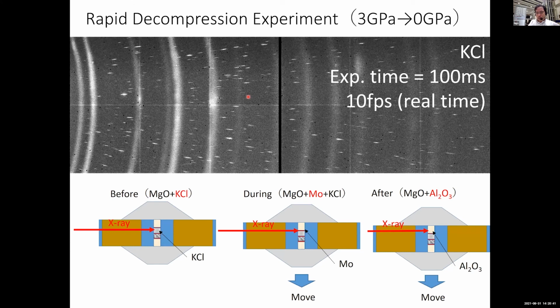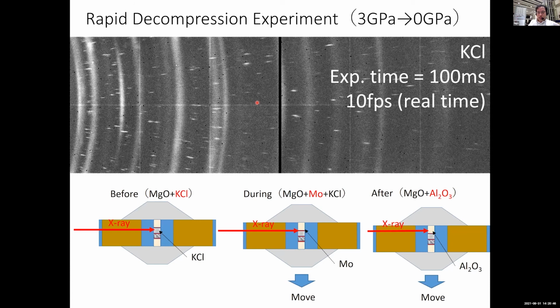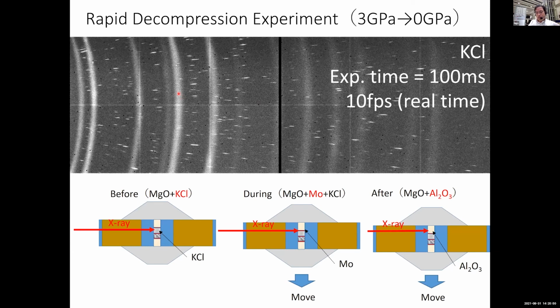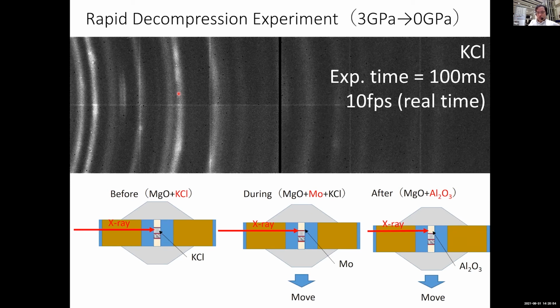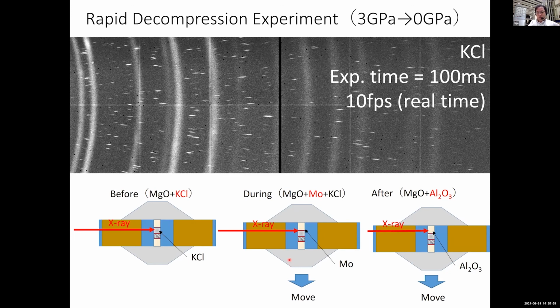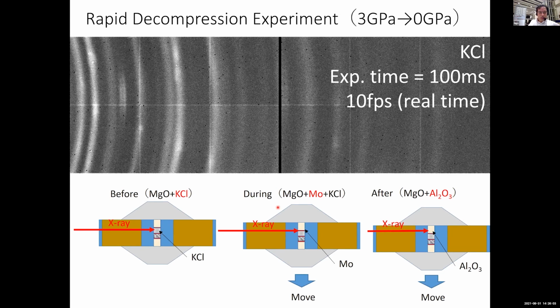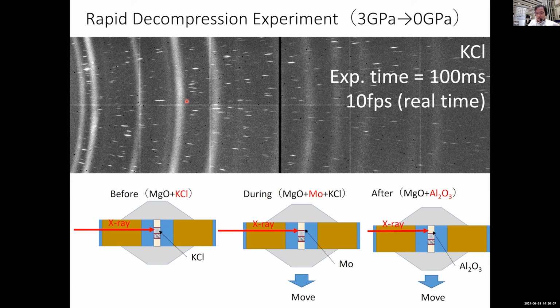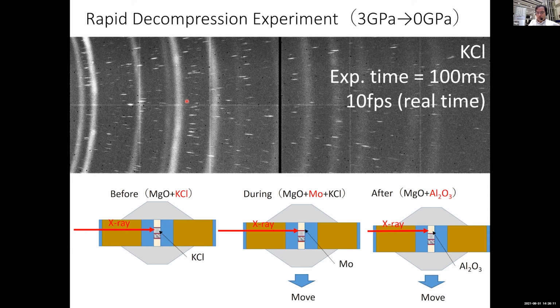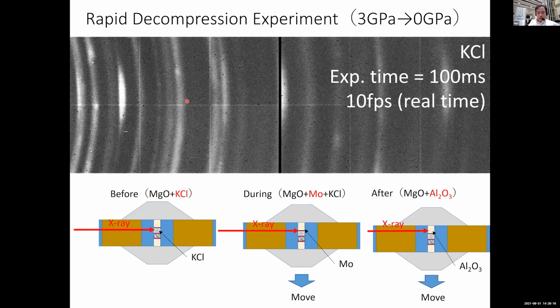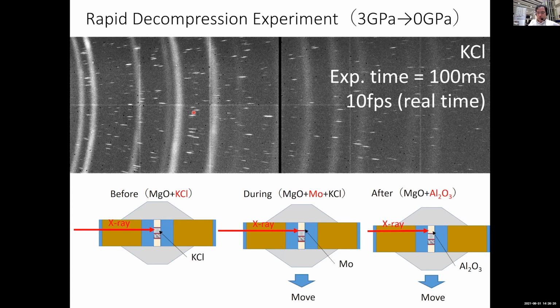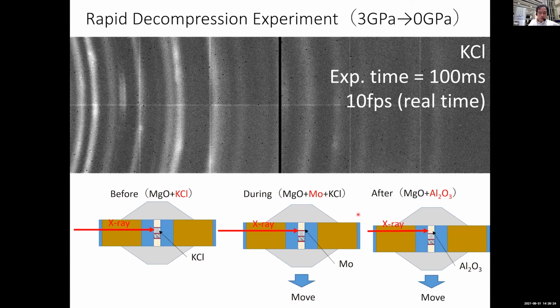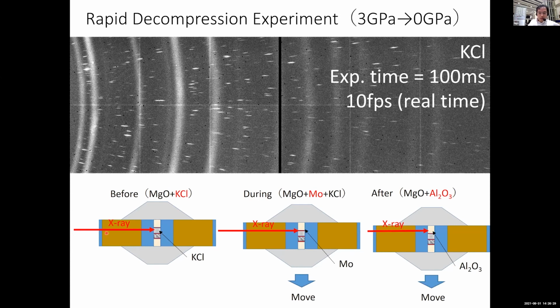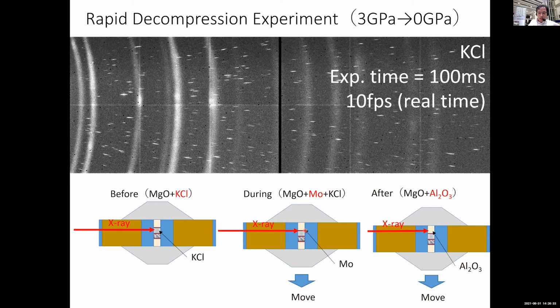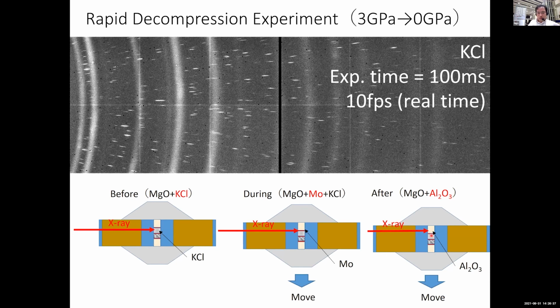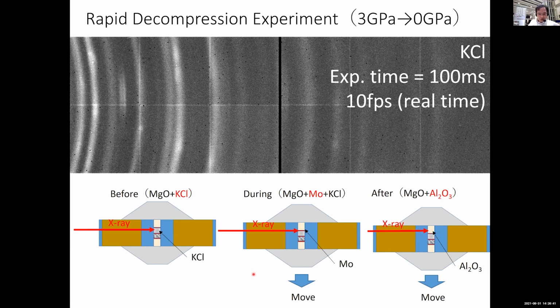Initially, we intended to see the change in the diffraction line of KCl, but as the high pressure cell moved down as the pressure was released, the diffraction line of the molybdenum appeared, and you can see this dot from alumina at the top of the sample appears. So first you can see this KCl, but when it starts to release the pressure, you can see this molybdenum foil and this alumina.